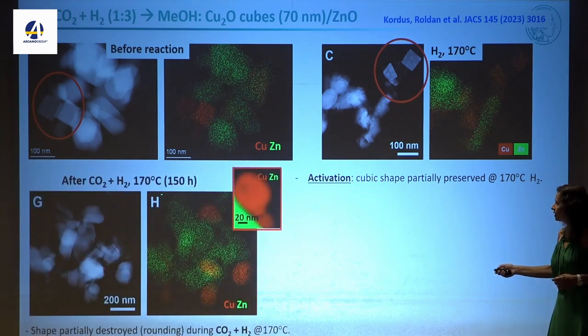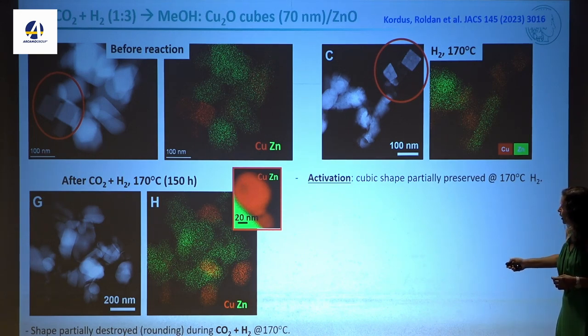But now we go to the same temperature, and we put the reaction conditions, and you see already the changes. So here I make this larger. You see the copper here. You are losing this nice, perfect cubic shape. You start to become rounded.